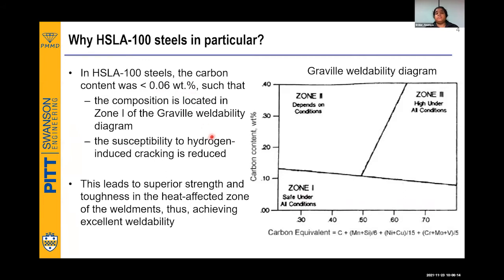And secondly, this main problem of hydrogen induced cracking. This hydrogen induced cracking is actually a delayed fracture. It is happening because of hydrogen. Of course, it is standing in water for a long time, so there is always a possibility for hydrogen to enter. And the problem with hydrogen induced cracking is that there is no guarantee that it will fail immediately. After the hydrogen enters and creates the embrittlement, it can either break today or break even after 2 months. So that is the problem with hydrogen induced cracking.